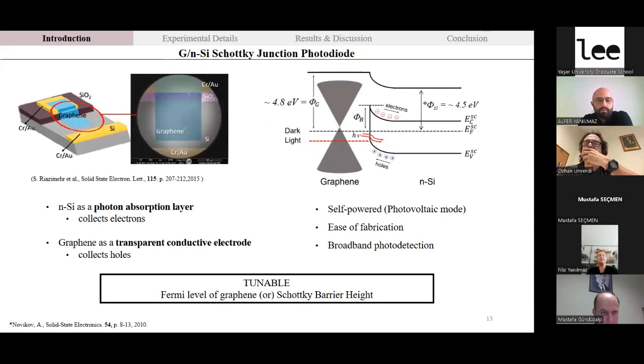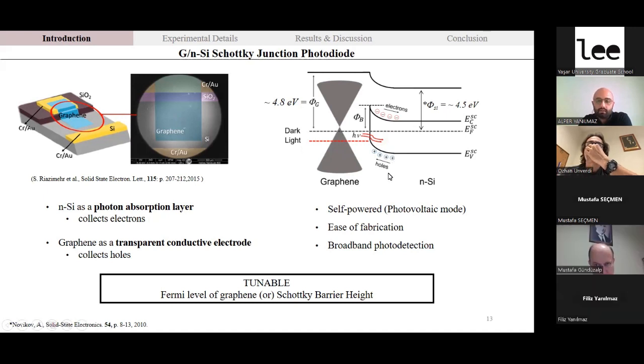What if we combine graphene and an N-type semiconductor like N-type silicon? Here you can see the studies on the combination of graphene and silicon heterojunction layer. Generally, N-type silicon is used as a photon absorption layer that collects the electrons, and graphene is used as a transparent conductive electrode and collects holes. Even under self-powered conditions, when you strike light onto the junction, electron hole pairs can occur easily due to the large electric field in the depletion region.